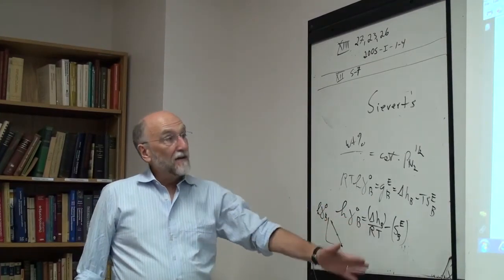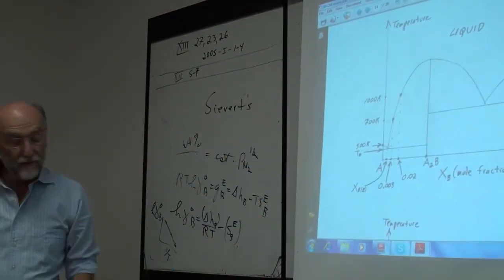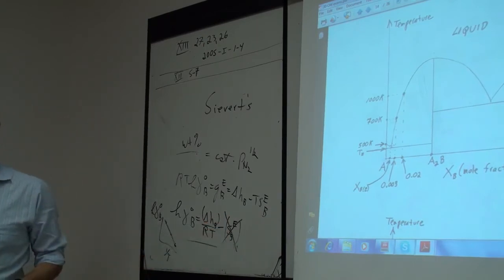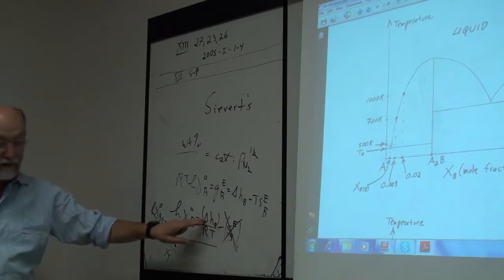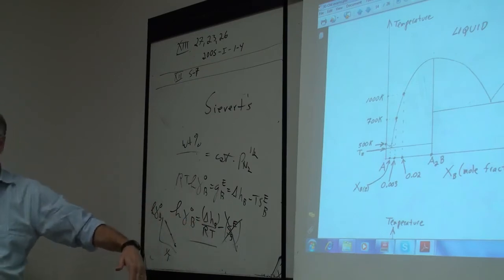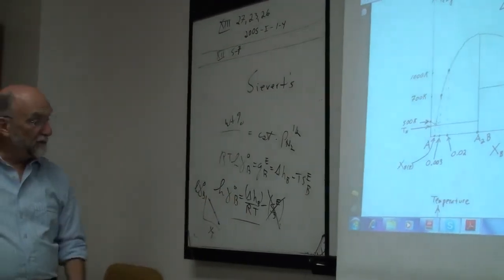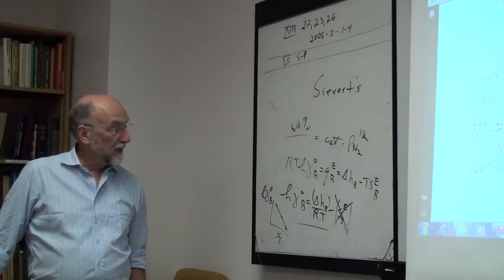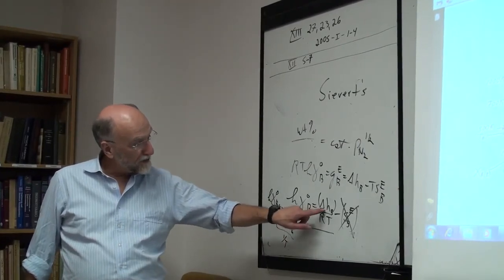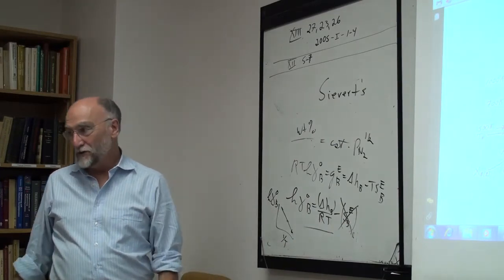If I only had 1 measurement at 700, how would I get it at 500? Even then, I wouldn't assume it was constant. I would simply set this to be 0, and do it that way, since this is usually smaller than that. So if you have 2 points or more, you do your linear extrapolation. If you have only 1 point, then do it this way. But don't ever assume that gamma is independent of temperature. That would be equivalent to assuming the excess heat was 0 and the excess entropy wasn't, which is not what you observe.